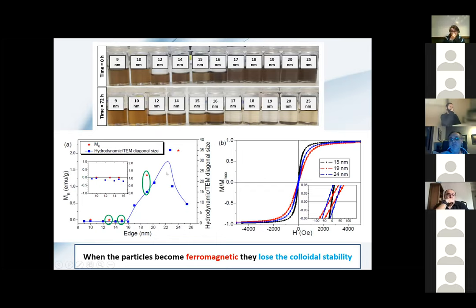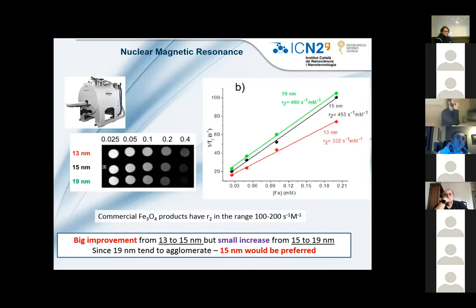And then we did some magnetic measurements, and we see that the coercivity of the small particles is zero, as we expect. You can see here the black curve, meaning that they are superparamagnetic. And as the size increases, the coercivity starts increasing, so the particles are no longer superparamagnetic. As the particles become ferromagnetic, they lose their colloidal stability.